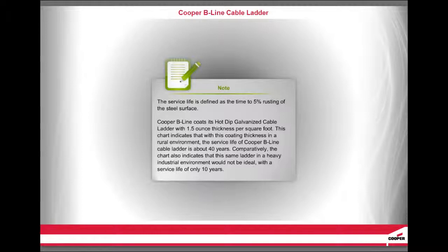Cooper B-Line coats its hot dip galvanized cable ladder with 1.5 ounce thickness per square foot. This chart indicates that with this coating thickness in a rural environment, the service life of Cooper B-Line cable ladder is about 40 years. Comparatively, the chart also indicates that this same ladder in a heavy industrial environment would not be ideal, with a service life of only 10 years.